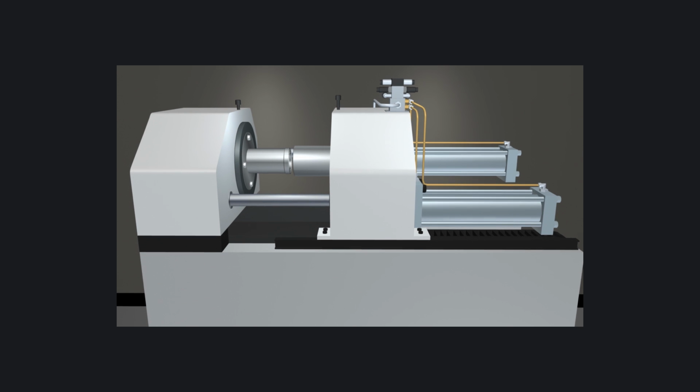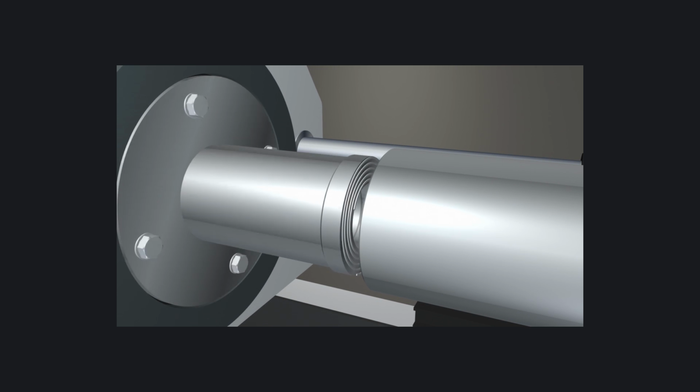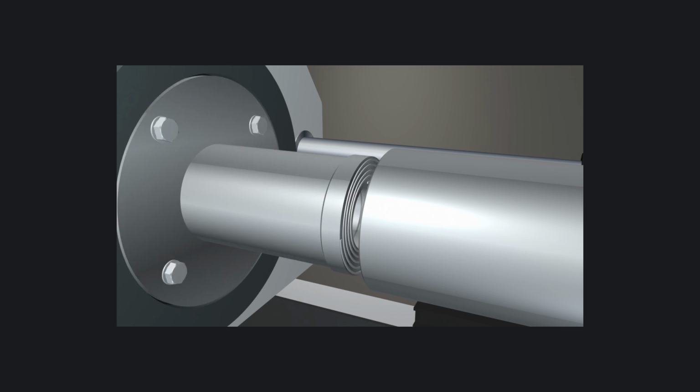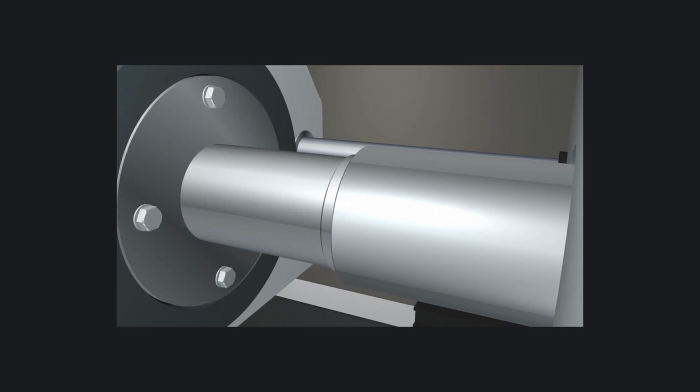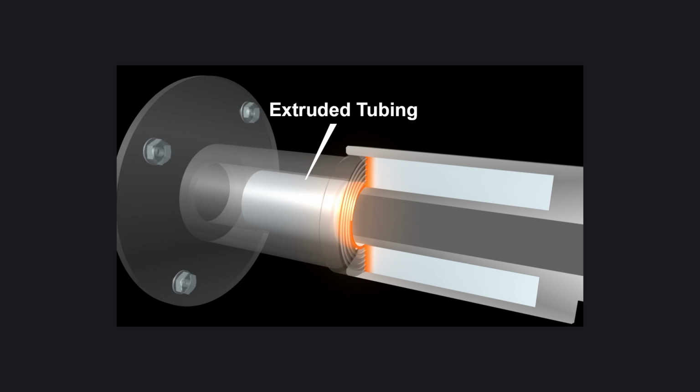ShAPE is a new way to put billets or flakes of magnesium through a die by spinning the metal. Friction creates heat to soften magnesium so it can be pushed through the die easily, and the rotation actually makes it better. The faster the metal spins, the smaller the grains become, which makes the end product more pliable.